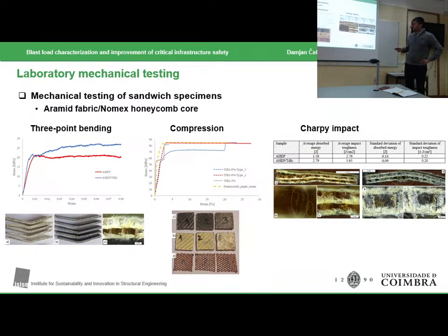We concluded from the study that adding the nanoceramics improves the bonding between the faces of the panel and the honeycomb. We observe in the non-reinforced specimens a small dent in every single one of the specimens tested, and we also see high delamination between the layers. Neither of these effects is present in the reinforced sample, and we can even observe a nice curvature of the specimen. Here we can also see the failure in the middle. If you zoom in enough, you will see the crack in the wall of the honeycomb.